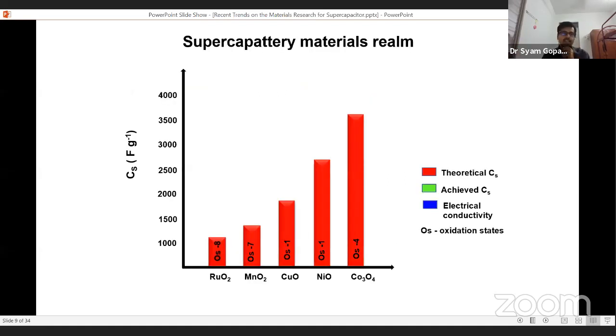Then if we look at the materials which are available for supercapacitors, we will find that transition metal oxides in particular are dominating, where ruthenium oxide and manganese oxide, as I have explained, come under supercapacitor materials. But other transition metal oxides like copper oxide, nickel oxide, and cobalt oxide also come under the supercapacitor materials realm. The theoretical capacitance, as we are observing, is higher for cobalt oxide compared to these materials.